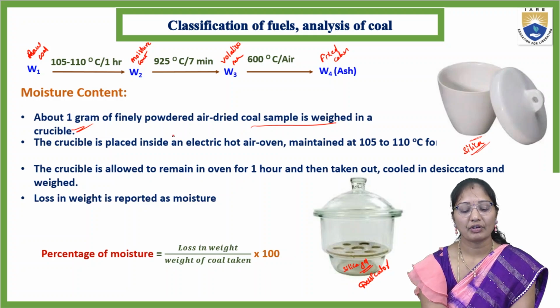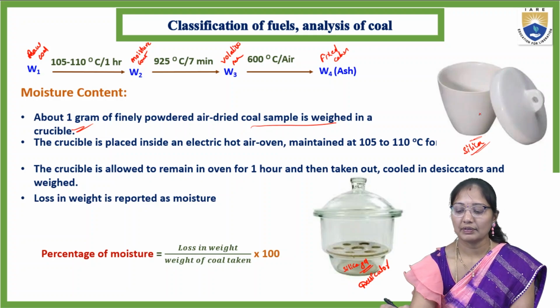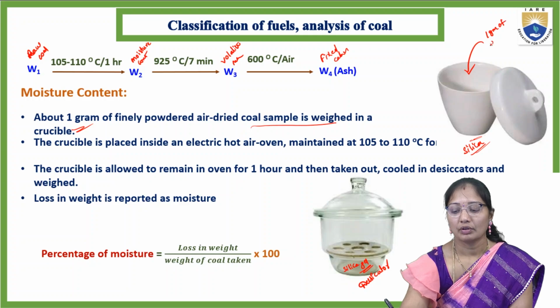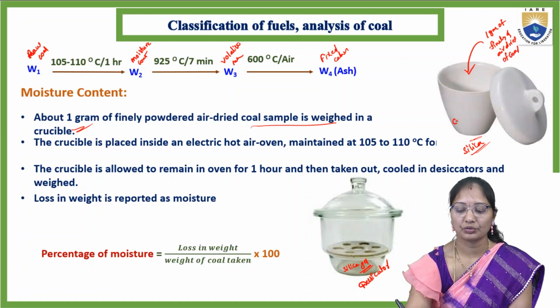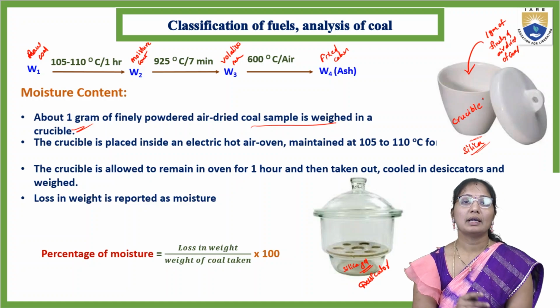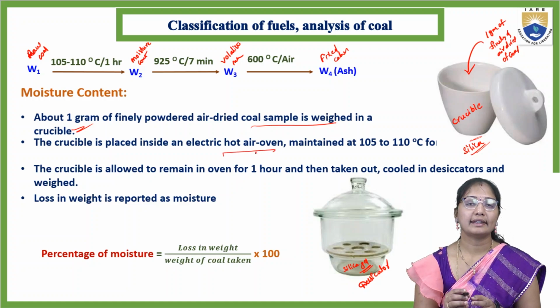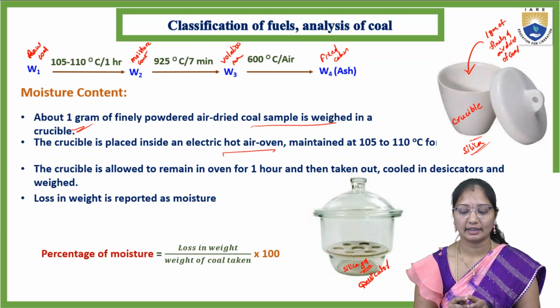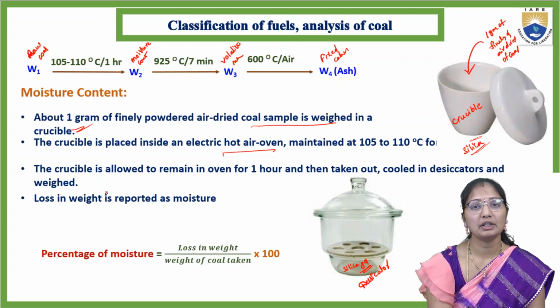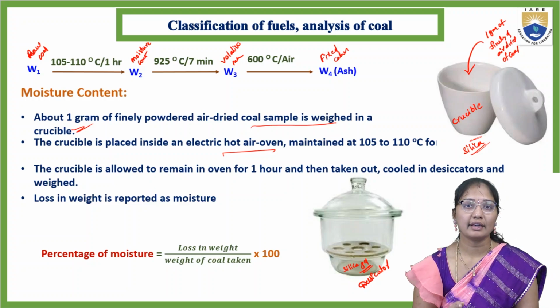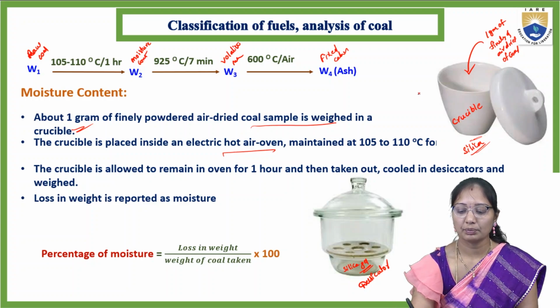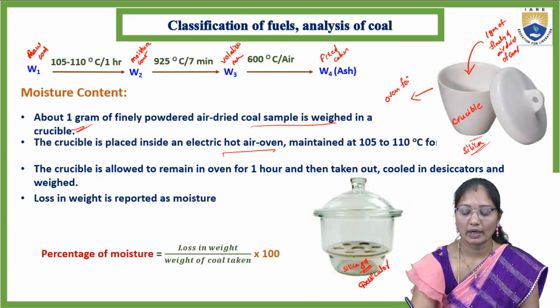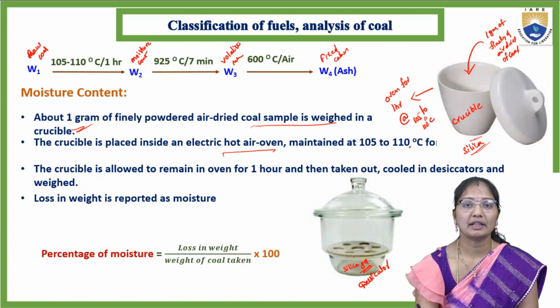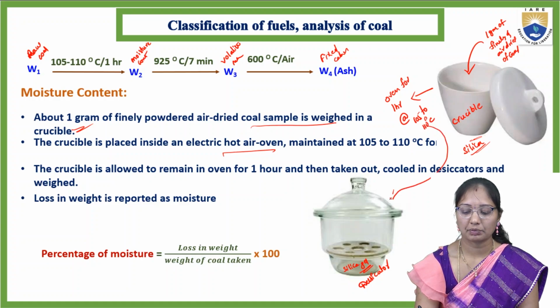So first, 1 gram of finely powdered, air-dried coal sample has to be taken inside this crucible. The crucible is placed inside the hot air oven and the temperature is maintained around 105 to 110 degrees centigrade for 1 hour. The crucible is allowed to remain in the oven for 1 hour, then taken out and cooled in the desiccator.